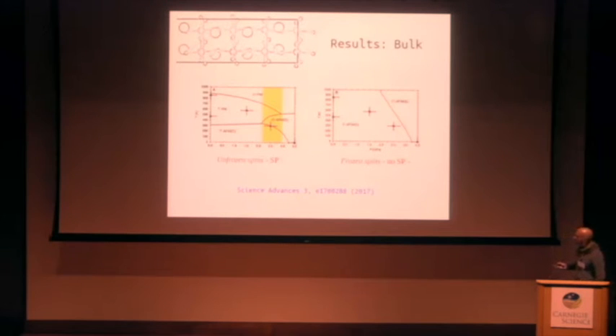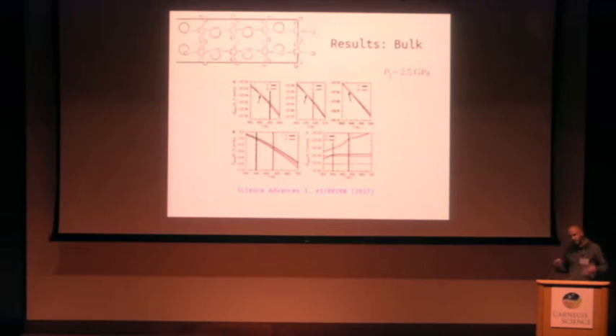If we further heat up the system, at some point we get the paraelectric paramagnetic phase, right? I have to say that this hasn't really been seen in experiments, but we think that's because the few works that have been done on this material have basically focused on finding the phase transitions in the high temperature range, right? They haven't really looked into these details. In any case, we hope that these results may motivate experimental searches for these kinds of effects that we are presenting here.